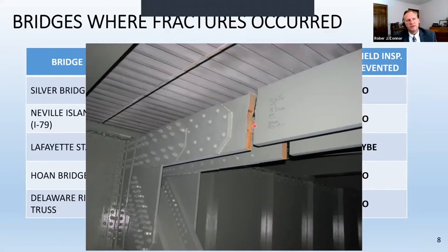And if you look close, you'll see two little darker spots here. That's from misdrilled holes. In fact, you see they line up with these rivets. And what happened was they misdrilled some holes. And in the 1950s, rather than leave the hole, they just filled it, sort of, with some weld metal. And if you then fast forward to the year it fractured just a few years ago,